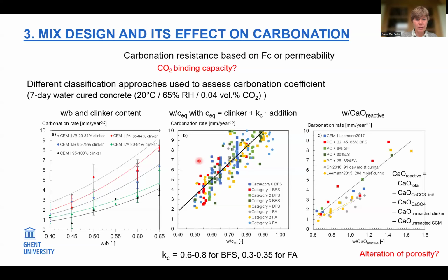Then secondly, we can use the K-value concept, where we replace the water-cement ratio by an equivalent water-cement ratio, in which we express the activity of the SCM as a fraction of the activity of Portland clinker. This is, of course, less simple because you have to know actually these K factors for each specific SCM.